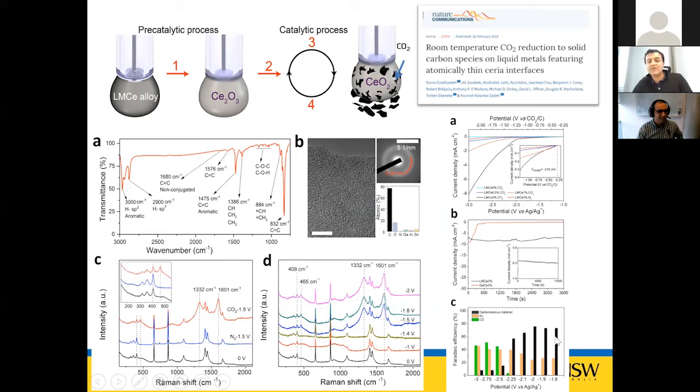Catalytic efficiency of the reaction is about 80%, and this is the first successful conversion of CO2 into graphitic material, rather than only looking at byproduct of something like liquid or gaseous form. We can have byproduct of solid form and still run the whole system effectively forever. So it introduces a very interesting prospect to the future of CO2 conversion.